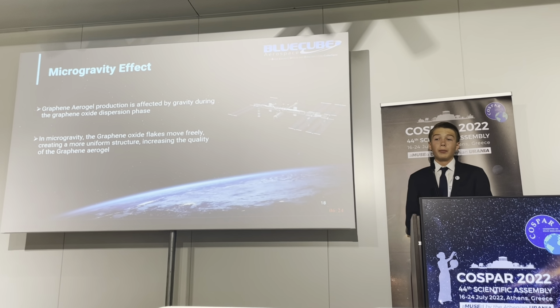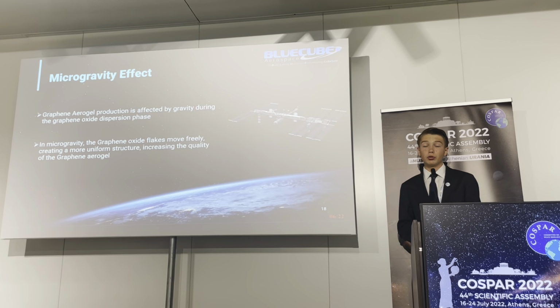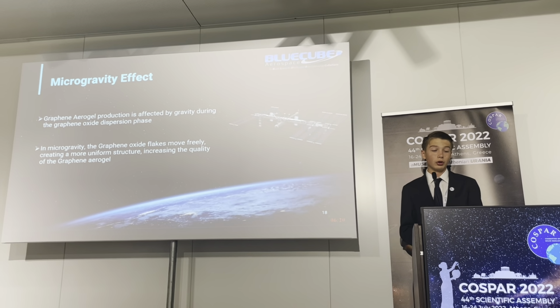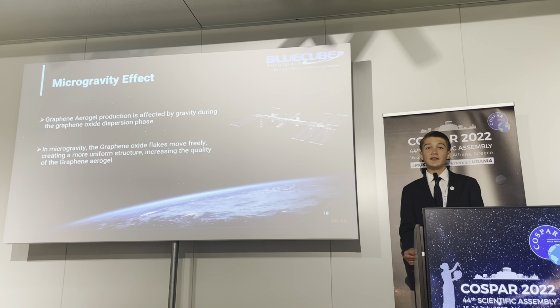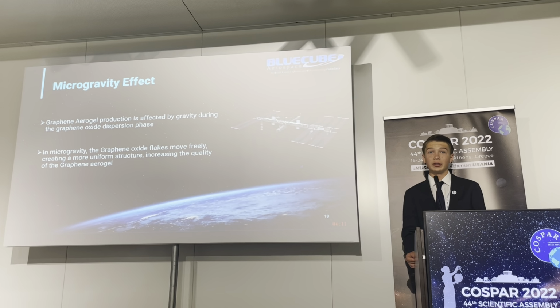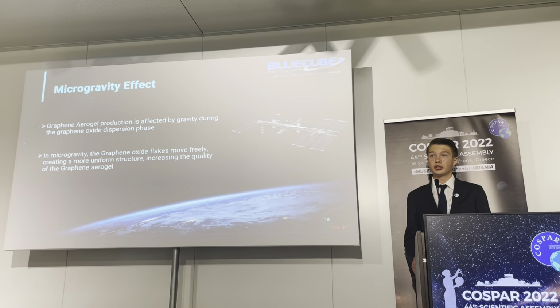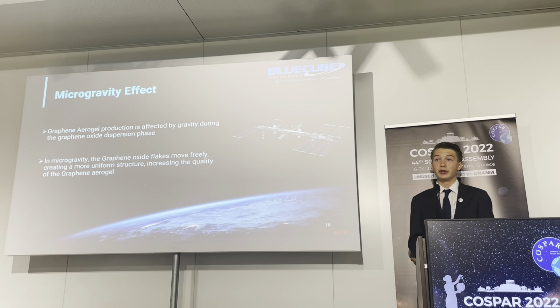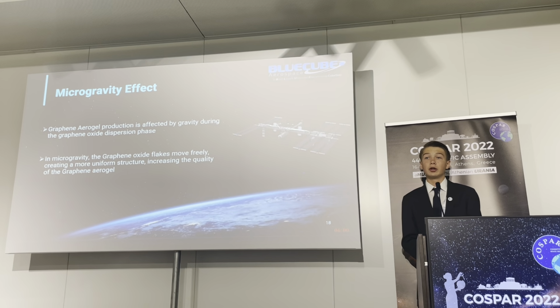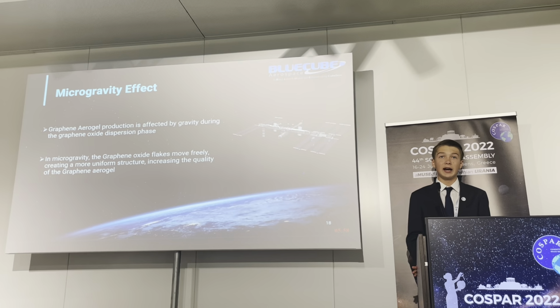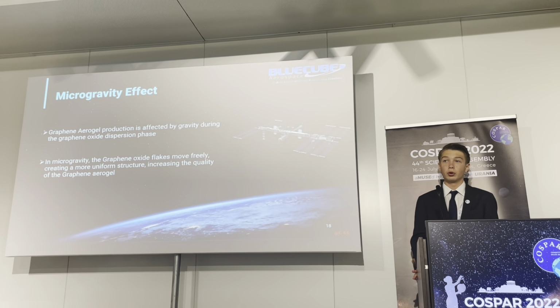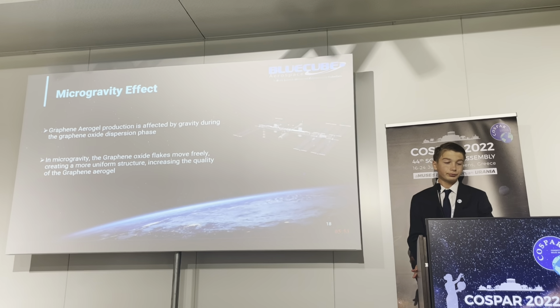The primary part of this process that is affected by gravity is the creation of the graphene oxide dispersion, because due to gravity, it pulls the graphene oxide flakes and water down, which creates an anisotropic or unevenly distributed graphene hydrogel, and then ultimately an unevenly distributed graphene aerogel. However, in microgravity, where there's not as much forces acting on this dispersion, it creates a more uniform macrostructure in the hydrogel, leading to a more pure and better performing graphene aerogel.